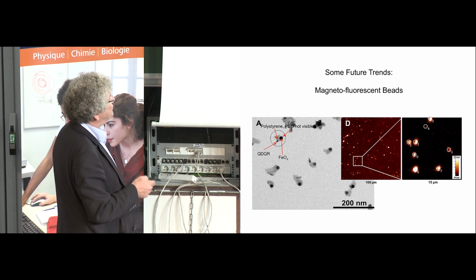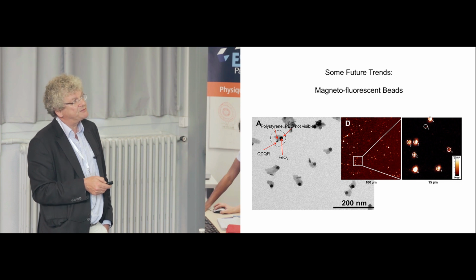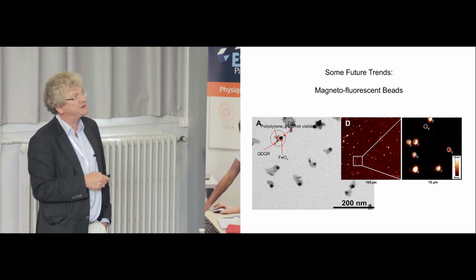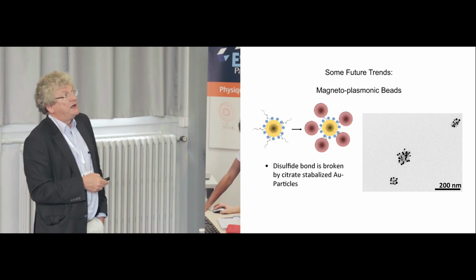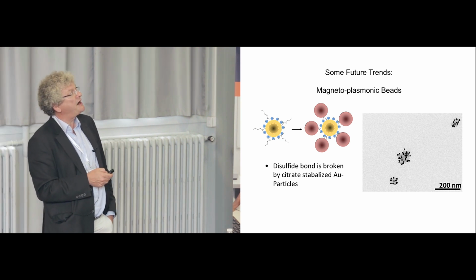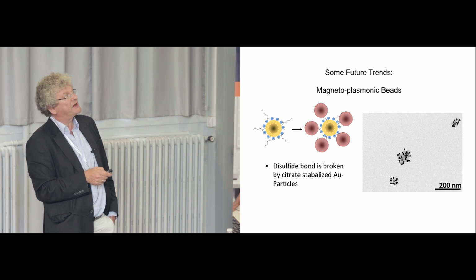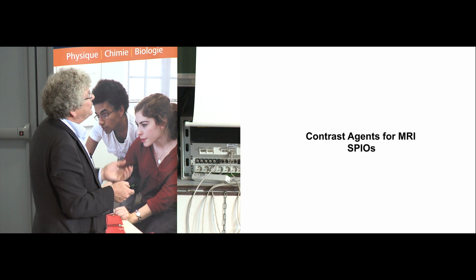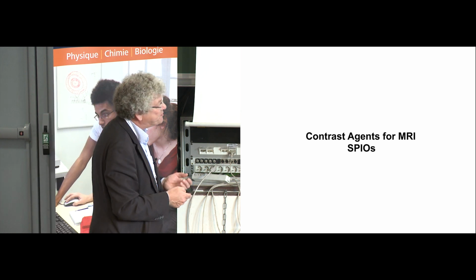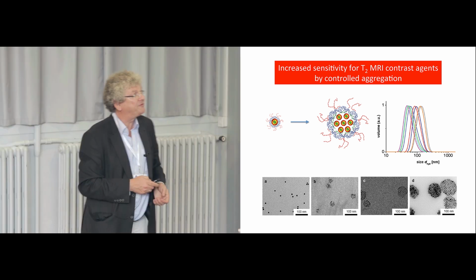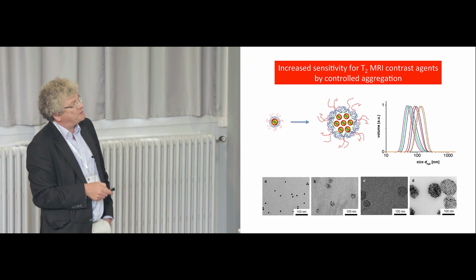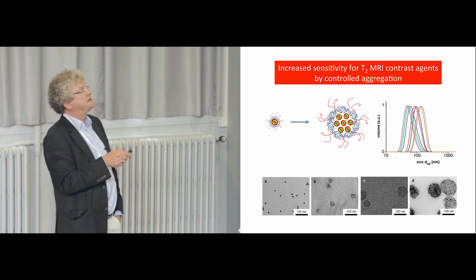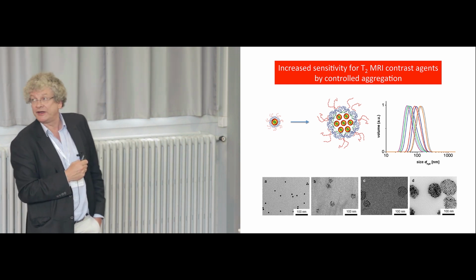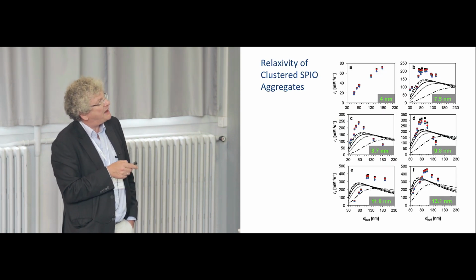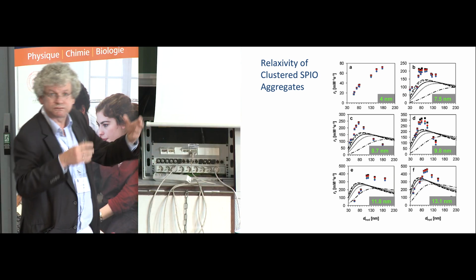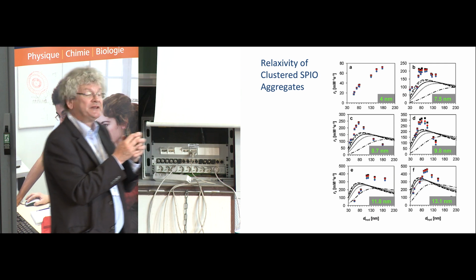Or making a little bit more fancy structures here, also the geometry of these systems is interesting. It resembles more like a virus with all these things there, and you have plasmonic and iron oxide. Or you use controlled clustering for MRI experiments. Here, one particle, and you aggregate them within one of these capsules, yielding then to differently sized particles. As you can see here, these type of raspberry structures, and they have very interesting properties in respect of their sensitivity in MRI experiments. So if you plot the hydrodynamic radius of these clusters against the sensitivity, the relaxivity as it's called in MRI experiments, then you see that at a given size here, you get an optimum where you have something like 20 or 50 nanocrystals aggregated in these particles.